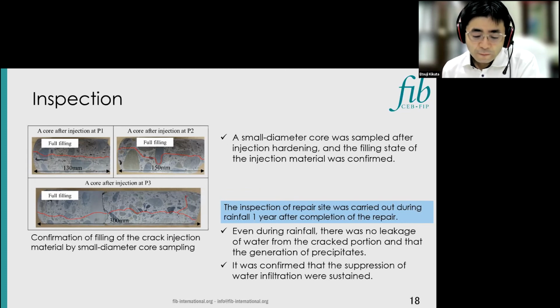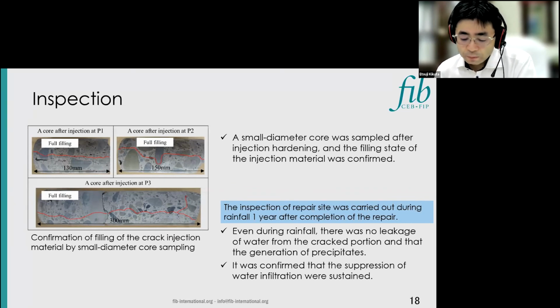Then, 1 year after execution of repair, the inspection of repair site was carried out because if early redeterioration occurs, there are many cases that occur within 1 year. It was carried out during rainfall in order to confirm whether there was water leakage. Even during rainfall, there was no leakage of water from the cracked portion and no occurrence of precipitate. From this result, it was confirmed that the suppression of water intrusion was sustained.